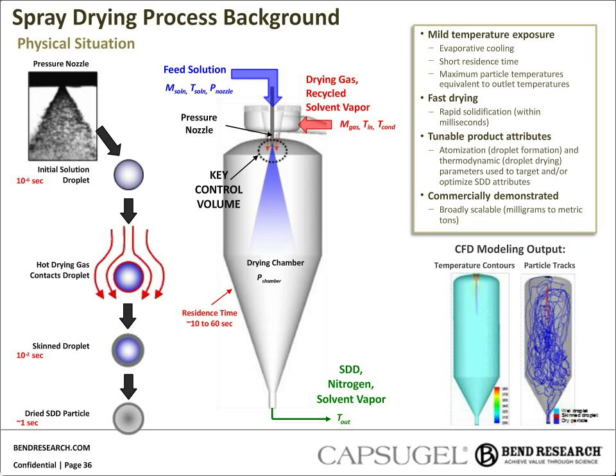The spray drying process has some key aspects that make it ideal for making amorphous solid dispersions. If we review the key physical situation, we see that the key control volume is up near the nozzle, where the droplets are formed by the atomizer and immediately contacted with hot drying gas. The drying happens very quickly, on the order of milliseconds. The skin forms and eventually further dries to a solid particle. This rapid drying or quench rate can enable kinetically stable dispersions above the thermodynamic solubility of the API in the polymer.